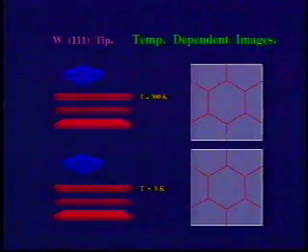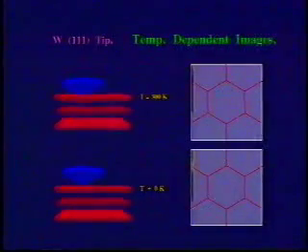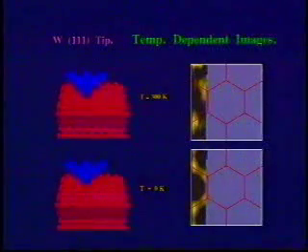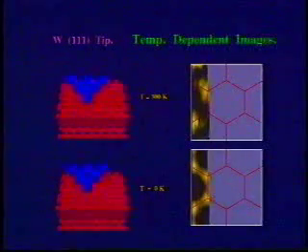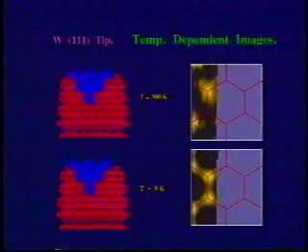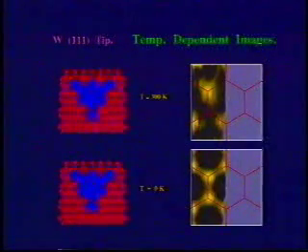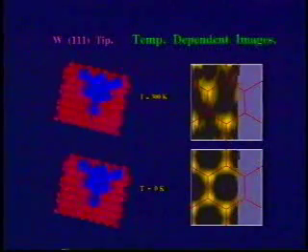The temperature of the probe and the sample crystal affects the scanned image. Here, the image from simulation, in yellow, is compared to the expected honeycomb structure of graphite, in red. At zero degrees Kelvin, all the atoms in the honeycomb structure are visible, while at room temperature, every other atom is missing due to their relative motion.